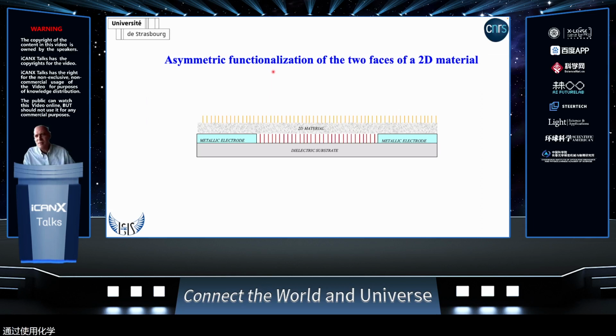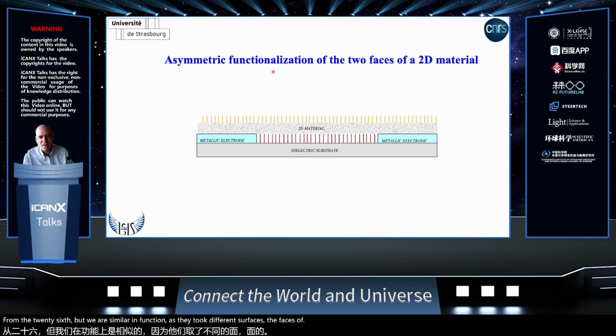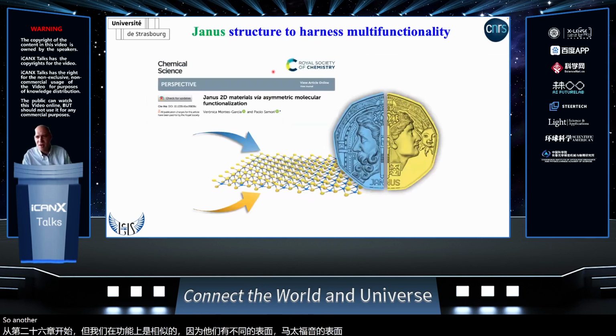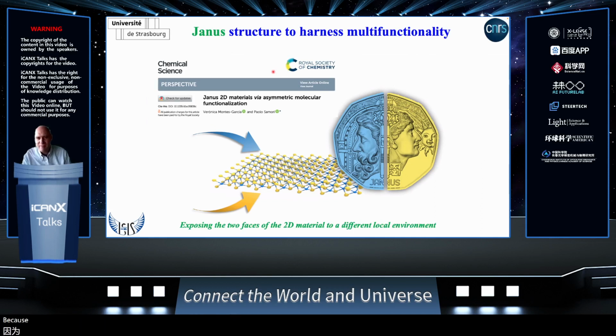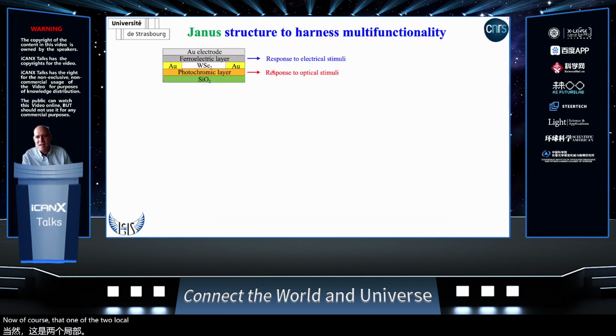And here we are dealing again with asymmetric functionalization, but not of the two electrodes. We asymmetrically functionalize the two different surfaces, the faces of the 2D materials. In other words, we use a Janus approach, or we fabricate a Janus structure, to harness multifunctionality, because the main concept is that we want to expose the two faces of the 2D material to two different local environments.